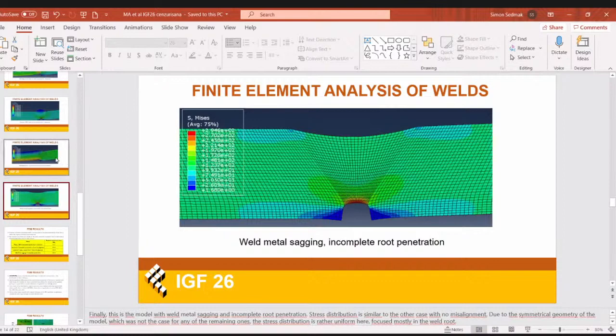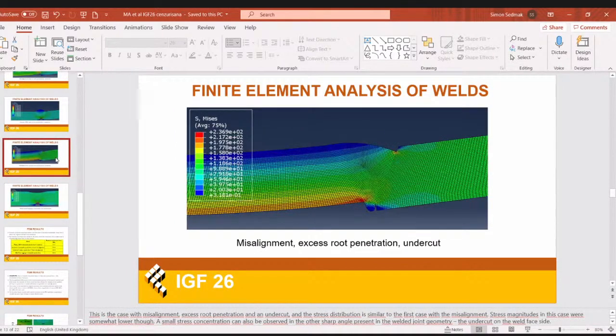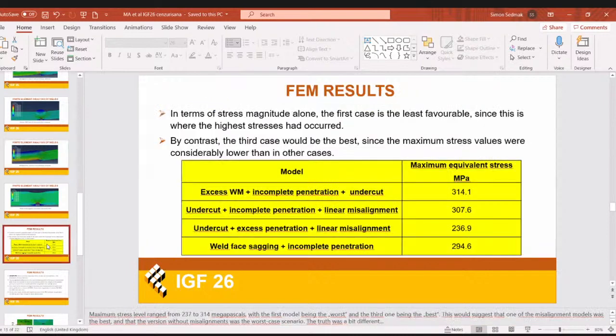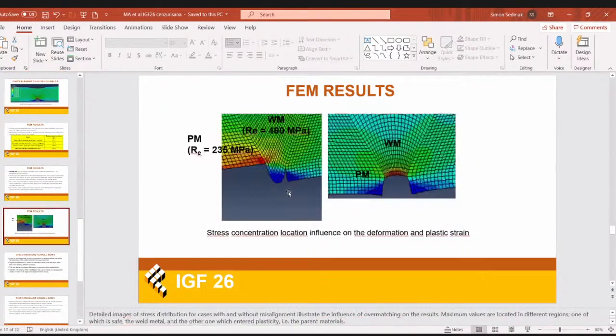The next stage would involve that once we determine the locations of stress concentrations, to include initial cracks in these areas to see how the welded joints would behave under those conditions. And here you can also see in more detail the stress concentration. For example, in the misaligned case, the maximum values of the stresses were around 240, while the yield stress of the parent material where this concentration occurred was 235. So there was plastic strain in this case.